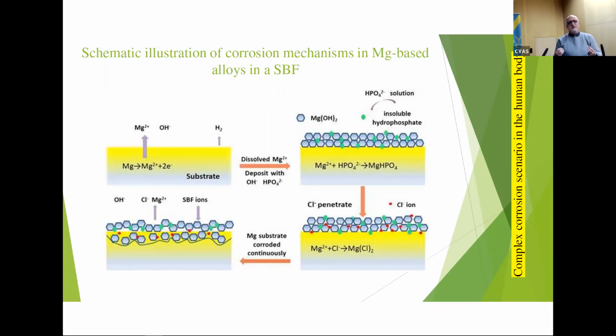That's a small illustration, just to know how it comes. That's the magnesium substrate. Some kinds of dissolution and reaction. Bubbles, and it also reacts with phosphate to give magnesium hydrogen phosphate. It's a kind of layer which protects from corrosion. But the chloride ion comes to destroy this layer completely, because chloride is very aggressive. So we do have magnesium, right? And like here, it's completely corroded. So you cannot use magnesium by itself. We have to make a kind of coating to protect it.